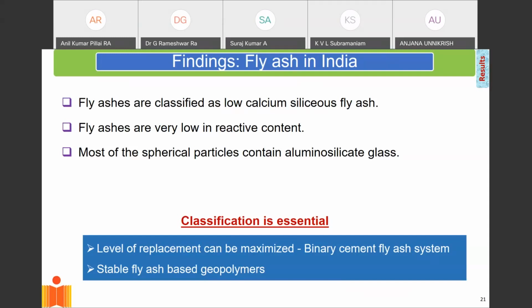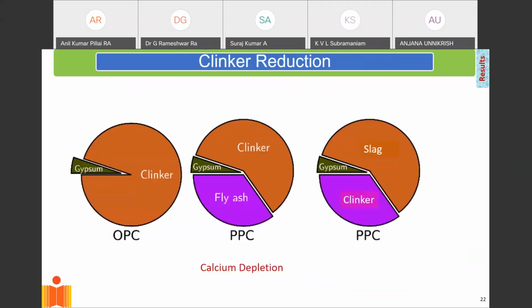So the code of practice currently caps off the replacement level at 35%. That's an average number that's given. But if we optimize it, we should be able to go higher or lower depending upon the reactive quantity that is present in the fly ash. But of course, that requires that we need to classify our fly ash. That is, all the fly ash that is being produced, we should be able to do an oxide analysis and then determine what is the optimal use.